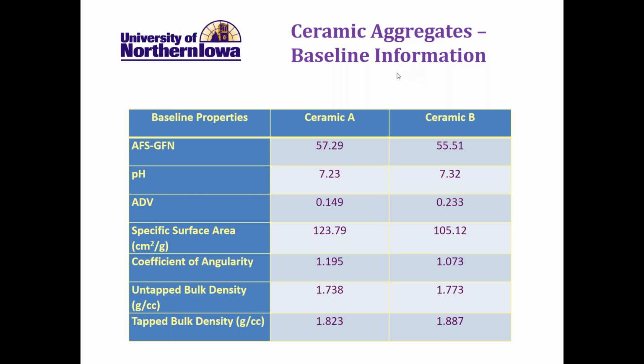Baseline information for the 2 ceramics we tested, they were both around 55 GFN. We chose that because that probably is a very common GFN for both iron and steel foundries. Similar pHs, similar ADVs, both very low. Similar specific surface areas, both very round in their shape, with similar densities.